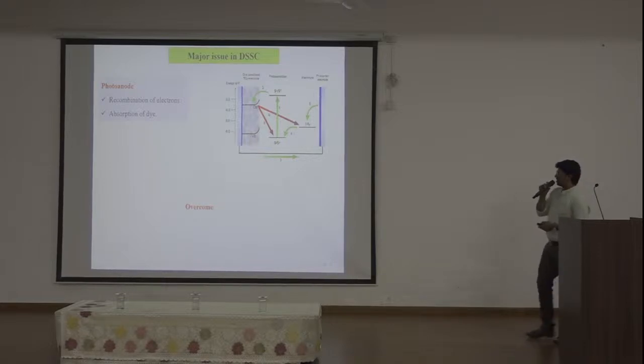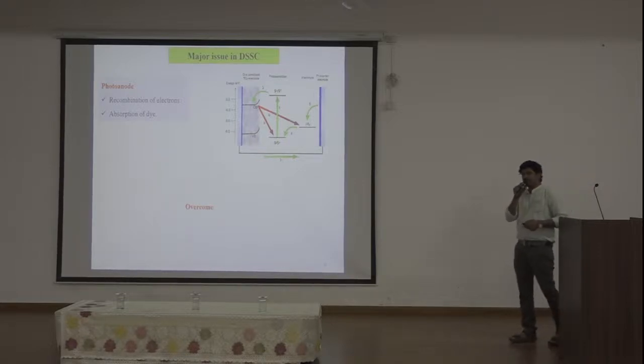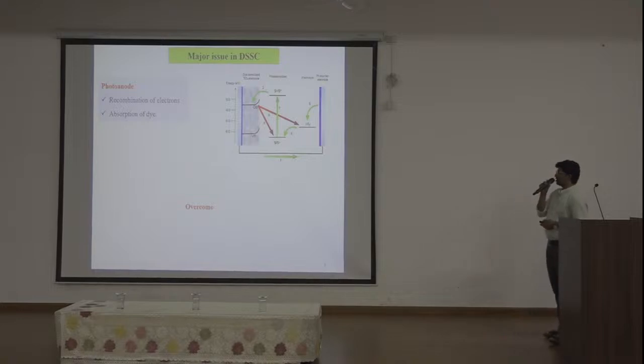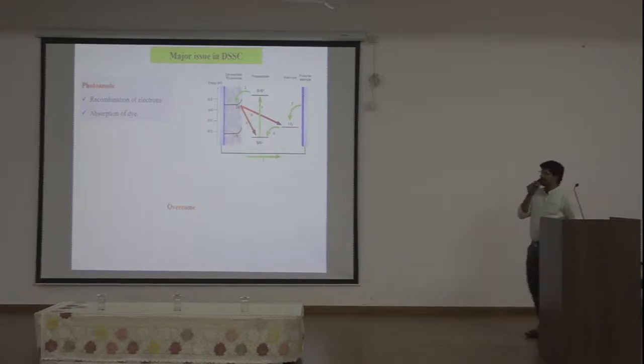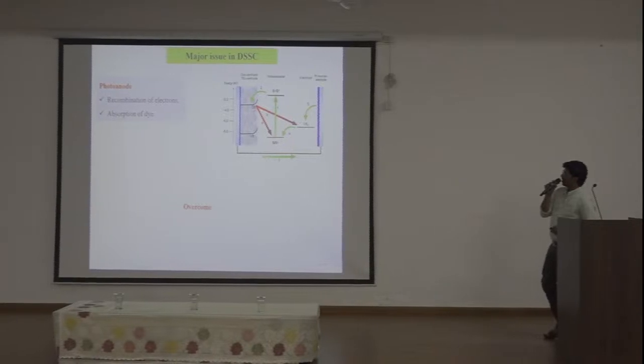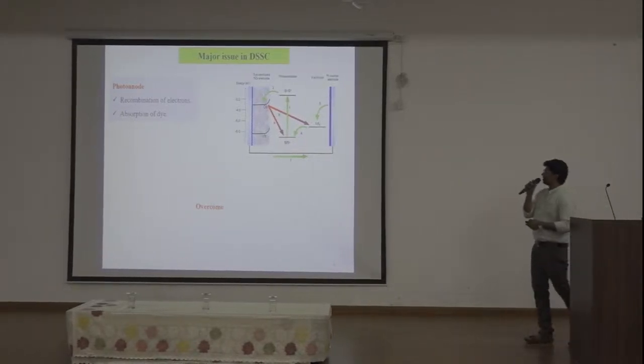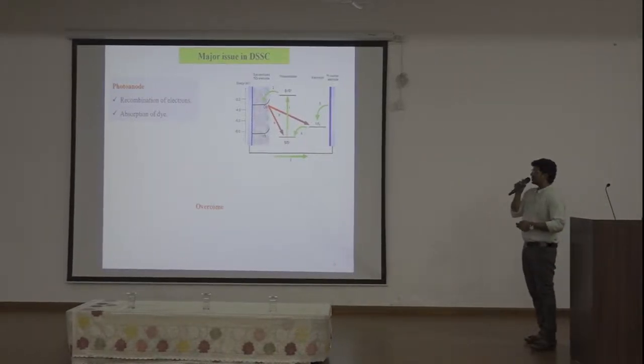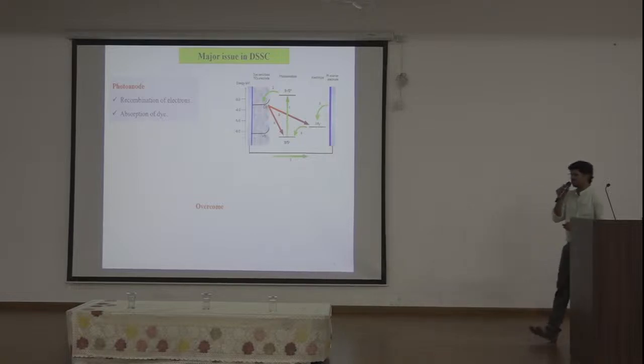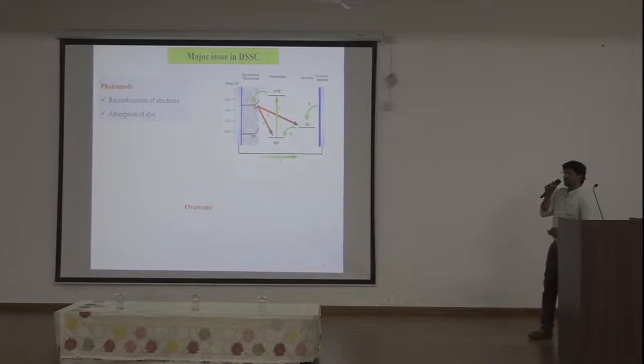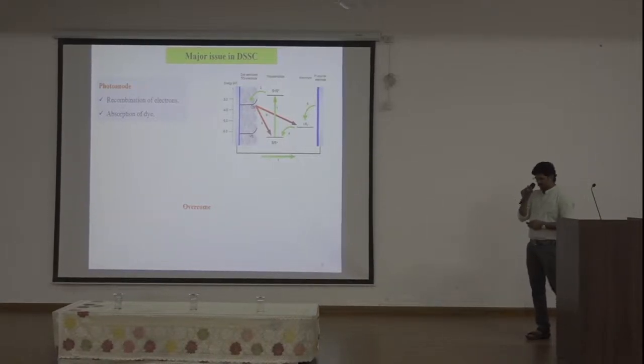But we know the charge injection and recombination are in thermal equilibrium, so people are working on a highly conducting layer to increase the charge injection efficiency, and they are modifying the structure, like a core-shell nanostructure, to increase the energy barrier and reduce the recombination reaction.